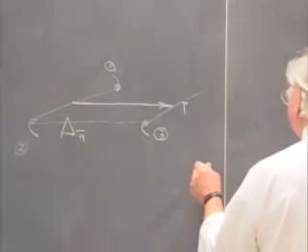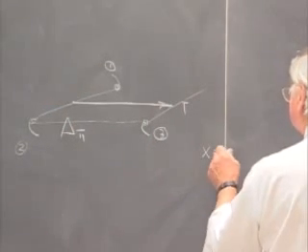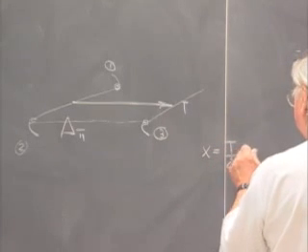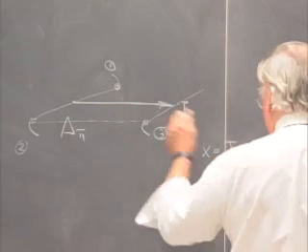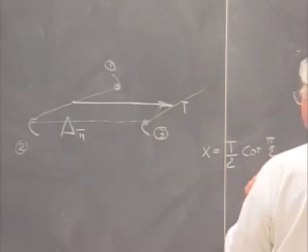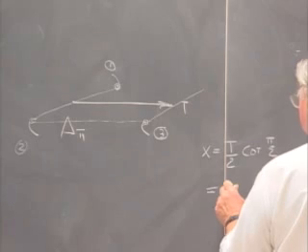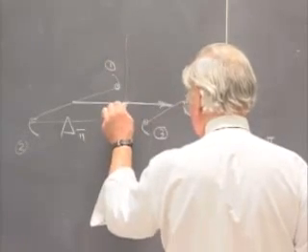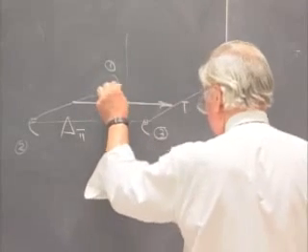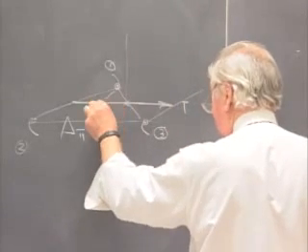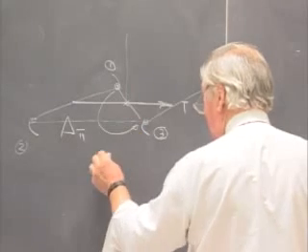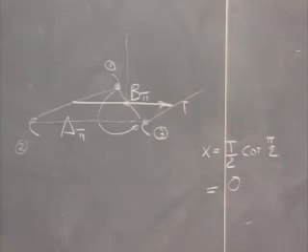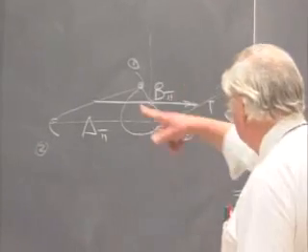Well, let's use our theorem. Our theorem says we should go a distance x along the perpendicular bisector, which is half the magnitude of t times the cotangent of pi over 2. The cotangent of pi over 2 is 0, so we go up a distance x that's equal to 0 along the perpendicular bisector, which means we stay put. And in this class, there's always truth in advertising. Around this locus here is a rotation operation b pi, which takes the first one into the third one.